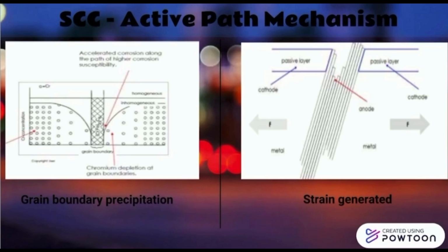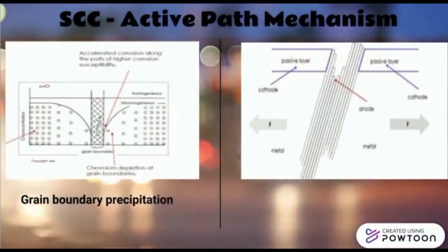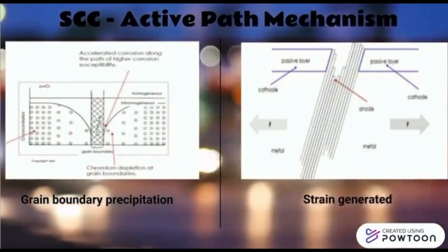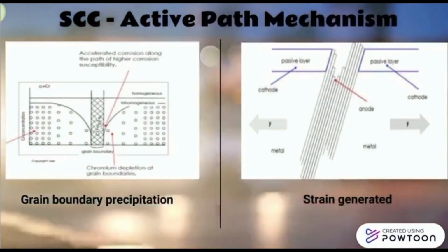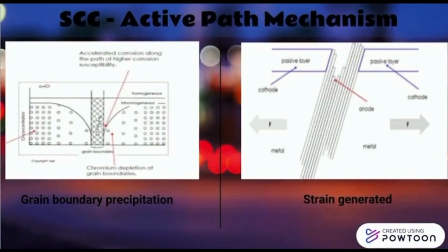For grain boundary precipitation, consequently, a form of corrosion can occur whereby the grain boundary corrodes while the specimen surface and the crack walls remain passive. This process can occur in the absence of stress, giving rise to intergranular corrosion that is uniformly distributed over the specimen. The effect of the applied stress is probably mainly to open up the cracks, thereby allowing easy diffusion of corrosion products away from the crack tip and allowing the crack tip to corrode faster.